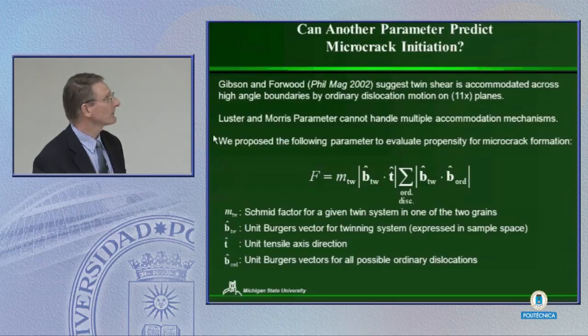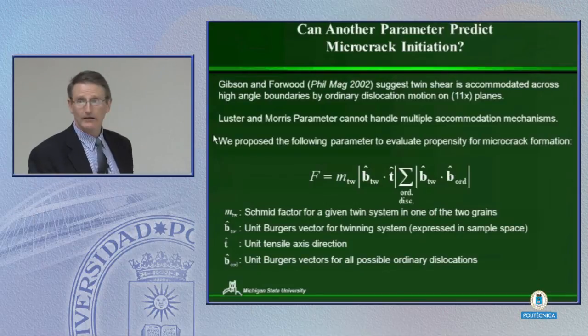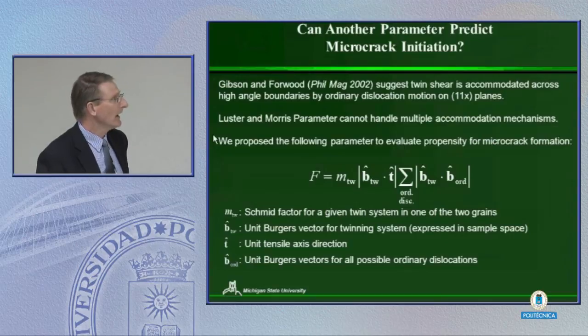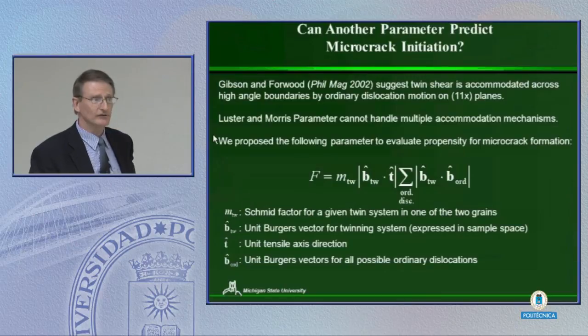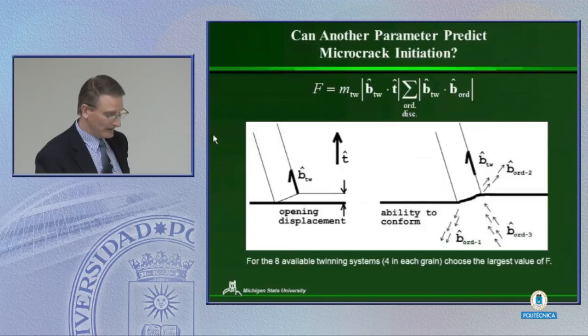So what we did is we came up with a different factor based on work by Gibson and Forwood, who suggest that the twinning shear in this material tends to be accommodated by dislocation motion. And we put together this factor here that takes into account a lot of things. First of all, the Schmid factor of a given twin system. In other words, how likely is it for that twin system to be active? How is the Burgers vector associated with that related to the tensile direction? Because if these are parallel with each other, it means that in general you're going to have more of an opening force on that boundary. And then how well can the twin shear be related to ordinary dislocation shear in the material? In other words, how well do these accommodate each other?